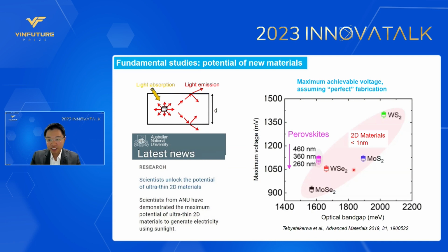The implication from this figure on the right-hand side is that, assuming your fabrication process is perfect, this is the best voltage that you can ever achieve if you use these materials to make a solar cell. For each step in making the solar cell, you will reduce this value a little bit if that step is not perfect. From this graph, we found that these new two-dimensional materials are very promising. They can give voltages higher than 1 volt. It is very possible to fabricate solar cells, but of course, 2D material is still quite new in the PV field.